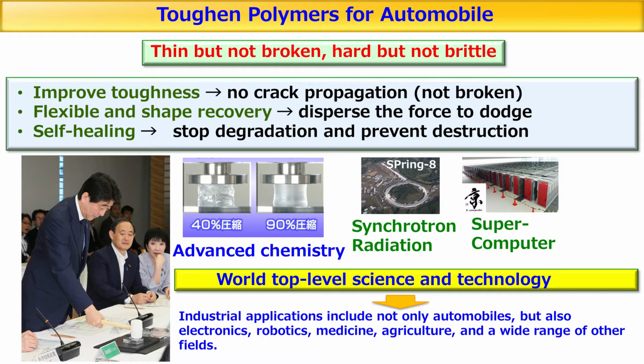cutting-edge science or chemistry, as well as synchrotron radiation and supercomputers were used so that toughness could be improved, even when a crack was present and not propagating. Even with a crack, if you apply force, it doesn't widen or propagate. It won't break. With flexibility and shape recovery, it can disperse the force and initiate self-healing, which is very important.